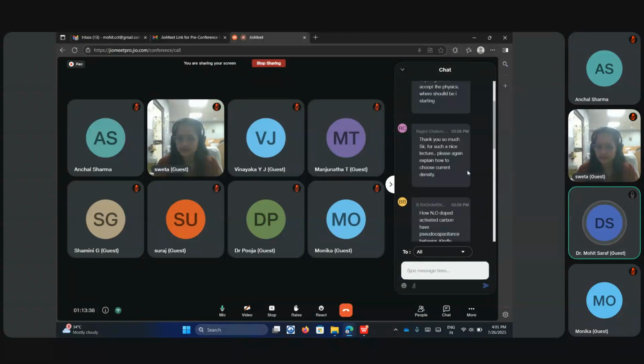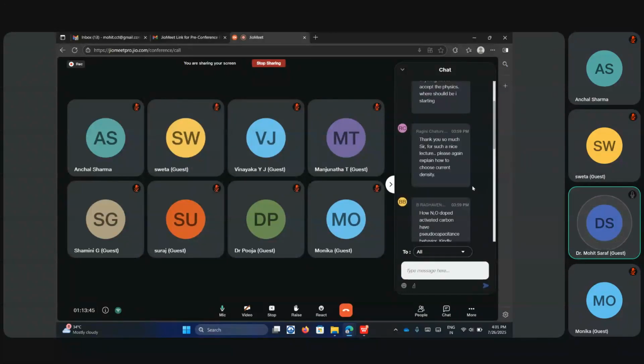Please explain again how to choose current density. Basically, when we talk about supercapacitors, we are interested in higher current densities, though there is no real high or low when we talk about current density. Let's say your scan rate in your cyclic voltammogram is 2 millivolt per second. If you go below that, you are transitioning into the battery regime, where we charge and discharge our cells very slowly. So if your scan rate is 2 millivolt per second, you check the timing, how long the upper half takes from one cutoff to another cutoff, and based on that you can choose your current density.